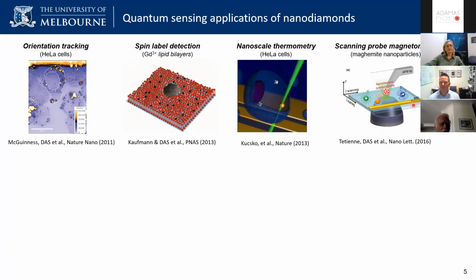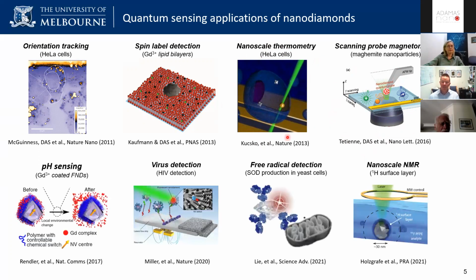And then Jean-Philippe Tétienne started to then explore putting nanodiamonds onto the end of AFM probes and then building up imaging platforms to image magnetic fields, temperature and electric fields and the like. In addition to those, there's been a lot of recent work which has really extended these applications. So Petr Cigler's group in Prague have been looking at functionalizing nanodiamond particles and making them sensitive to pH, for example, and using T1 to monitor the presence of gadolinium around these particles. There's been some really nice work done in terms of virus detection and using the spin properties of the NV centers to enhance the sensitivity of these standard bioassays.